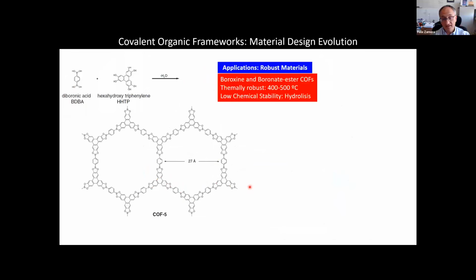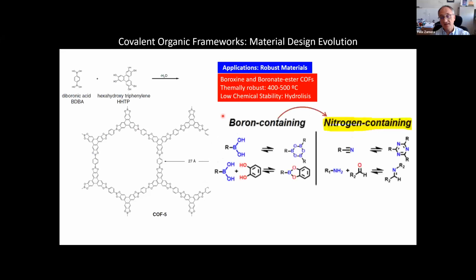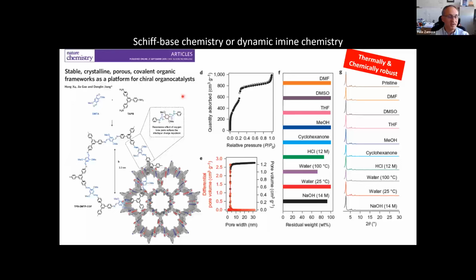But all this chemistry is nice, and the materials that you can form are thermally robust, but most of them can suffer hydrolysis when you try to apply these materials for some particular applications. And then they are not very robust. Several research groups switched from boron-containing to nitrogen-containing COFs, because, as I'm going to show you, these new imine-based COFs are chemically more robust. In here, this example that I collected from Dongyang's lab shows the possibility to form this extended network, this COF based on imine bonds, just by condensation reaction between this dialdehyde and this triamine.